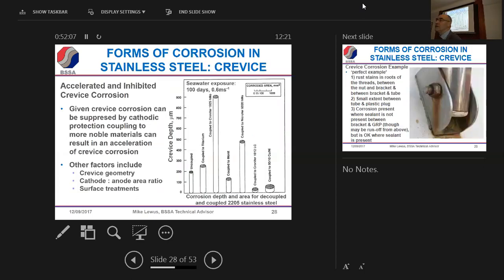I'm going to skip through some of the slides and be very quick about them, only because I think I'm sort of running out of time. We can actually protect against crevice corrosion and pitting corrosion by just using standard cathodic protection techniques. But by the same token, if we couple that material to a much more noble metal, we can accelerate it as well. And this is just to illustrate the point, a plot of 2205, which is a duplex grade. That's actually called the standard duplex grade.